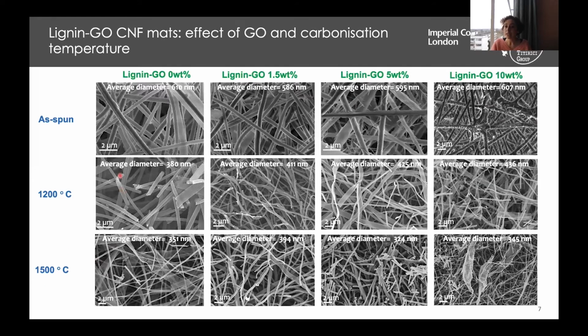And what we observe is that when graphene oxide is not present in the fibers, this carbonization temperature is enough for destroying almost entirely the structure of the fibers, because of the templating porous effect that gives the sodium hydroxide, which is the activating agent, and therefore also templates a porosity there. When graphene oxide is present, then this doesn't happen, probably because graphene oxide is reinforcing the fibers and gives them a stability for this carbonization temperature.